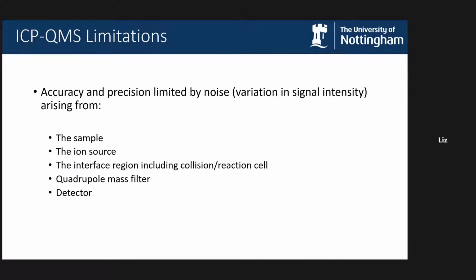That accuracy and precision is limited by noise in the signal, so variation in the signal intensity. And that arises from a number of sources with a quadrupole instrument. So it'll arise from your sample itself, typically the sample matrix, variation in the total dissolved solids in the sample and between the sample and the standards. And then you have the ion source, you have the nebulizer and the spray chamber system that's used to introduce your sample into the plasma and the plasma itself. And then you have an interface region where you have optics for focusing the ion beam, and sometimes a collision or a reaction cell that might be primed with different gases, etc. And then you have the quadrupole mass filter that can introduce noise, and then the detector itself.